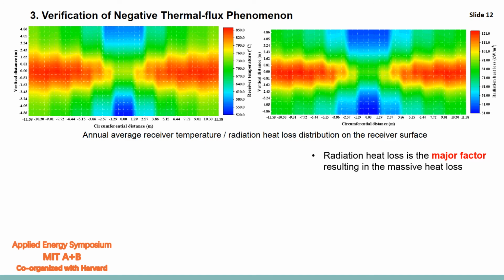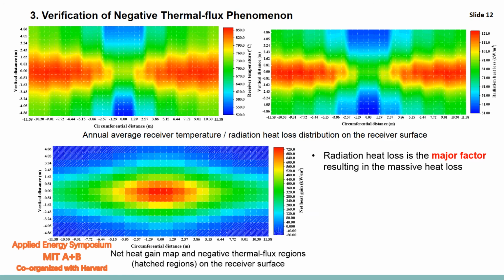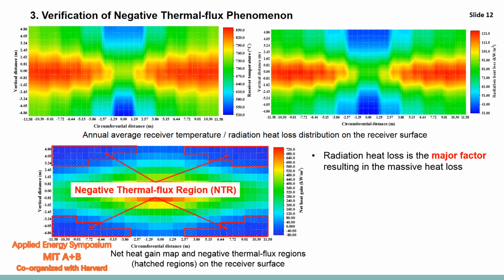major factor resulting in the massive heat loss of the whole tower receiver. Based on the obtained solar flux and heat loss distributions, we calculated the net heat gain of each region in the receiver. Just as we expected, a negative heat gain phenomenon occurs at edge regions close to the southern side. We call these regions the negative thermal flux regions, that is NTRs. It is calculated that the number of the NTRs reaches 111, almost a quarter of the entire receiver, which seriously affects the thermal performance of the tower receiver.